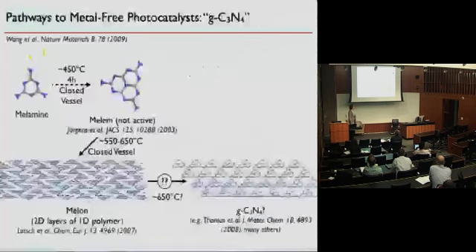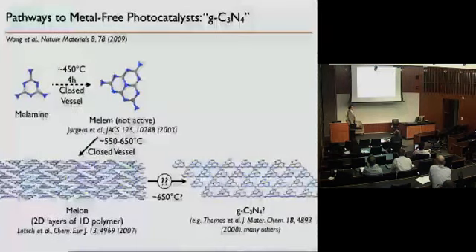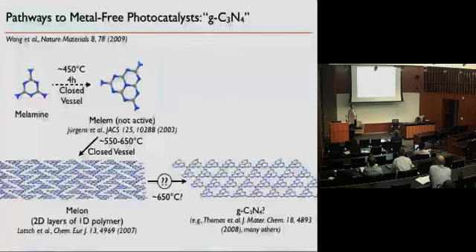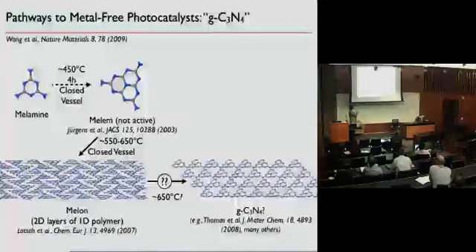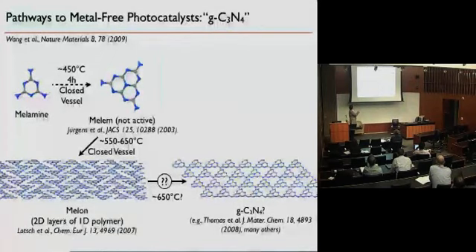So one class of materials that we got involved in certainly has some of these characteristics, and this is carbon-nitrogen-based materials, which are made of obviously abundant elements. The synthesis process, this is a complex slide, but the key point is the synthesis process is relatively easy. You take a simple precursor molecule, heat for a while under certain conditions, you come to this molecule, you heat some more, and you come to this layered structure here. That's an actually active compound. This was realized about 6 years ago, and since then the activity on those materials has exploded.